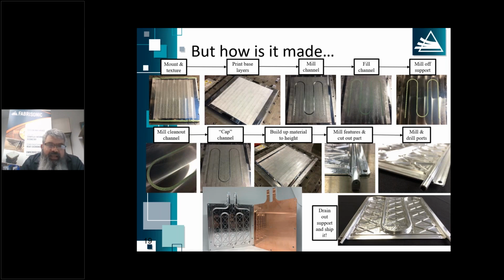We then mill that to get a nice, flat, even surface. And then we continue to print metal foils layer by layer over top of those channels to fully encapsulate those. When we get done with all of our printing, we come in with the mill to get the exact geometry, in this case, an isogrid that we're looking for on the outside of the part.